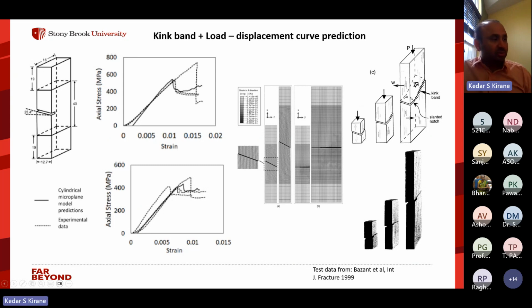In fact, I don't think there are any other papers which show this kind of agreement in terms of the peak, the small drop, which represents the formation of the kink band, and then this plateau, which shows local rotation, localization of the shear in the kink band, and frictional sliding in the kink band. So all these features, our two-scale approach of the microplane modeling strategy, it seems to work very well.